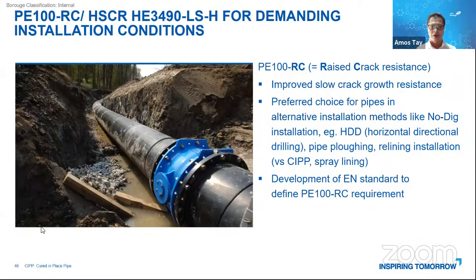All right, now we talk about this RC. What is RC? PE100 RC is raised crack resistance, or HSCR, high stress crack resistance. This has an improved slow crack growth resistance, which Pixel has shared earlier, the graph. When you have a cut in the pipe surface, this growth will take time and grow through the wall thickness, and then the pipe integrity will be suffered.